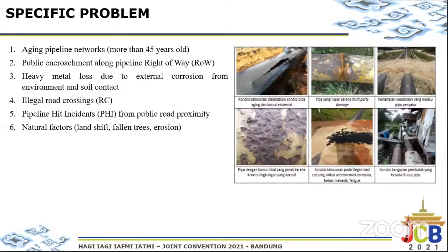As part of further pipeline integrity problems, inline inspection or ILI and long-range ultrasonic testing or LRUT were conducted on the existing aging pipelines to be used as baseline data. The results indicated some pipeline segments were at high risk due to significant metal loss. We can see in the picture some conditions of main corridor pipelines: pipeline leaks due to illegal road crossings, corrosion, and also encroacher houses or facilities near the pipeline.